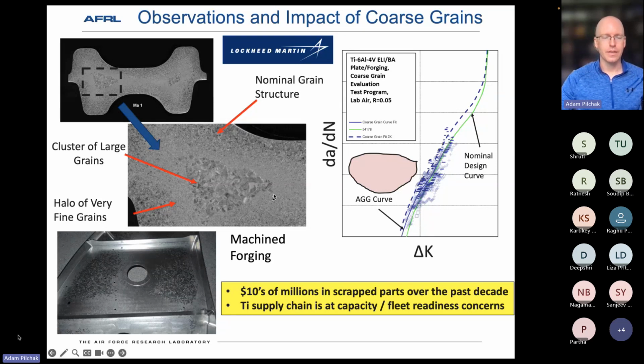Interestingly, this is usually surrounded by what we're calling the fine grain halo here. So very stark contrast and pretty sharp interface between these really coarse grains and really fine ones. And we'll get into the source of that in a little bit. But then eventually you get away from there and you get the typical expected microstructure. And so in this case, the nominal beta grain sizes are of the order of a millimeter or so, and